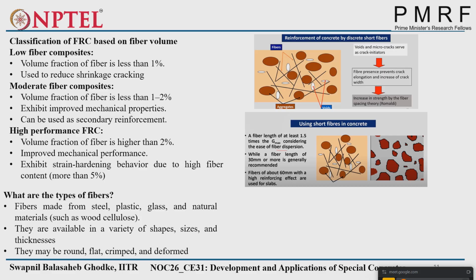Okay. Now you can tell me, anyone, here we are saying the length of the fiber should be 1.5 times the diameter of the aggregate. So if here it is recommending that 30 mm fiber length will be there, what will be the maximum diameter of the aggregate? Right, 20 mm. So in this case, they are recommending 20 mm maximum size of aggregate. In that case, you can use 30 mm of fiber length.